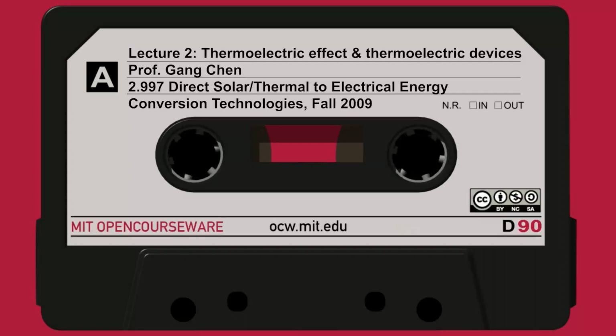Okay? So the other point is, you look at this, you say, the familiar term, this term is all thermal engine. That's a Carnot cycle for refrigeration. We wrote down Carnot for power generation. But this is a Carnot. So it's a Carnot factor, it's a heat engine. And of course, you want to make sure this term is less than 1. Right? You can't beat Carnot. And here came this factor Z. That's thermoelectrics. Every time people see you, what's your ZT? This is where it came from. Z times temperature. And this T is the average temperature between the hot and cold side.